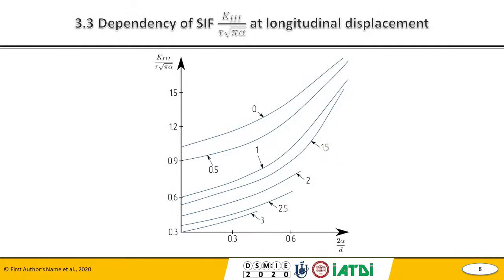Dependence of the stress intensity factor on the relative distance between the sections of delamination during longitudinal shear. In the case when, due to the roughness of the working surface, there is a system of sections of delamination of the coating from the base material, it's possible to change the stress intensity factor due to their mutual influence.